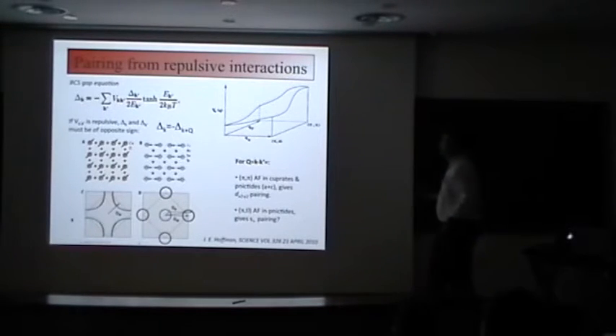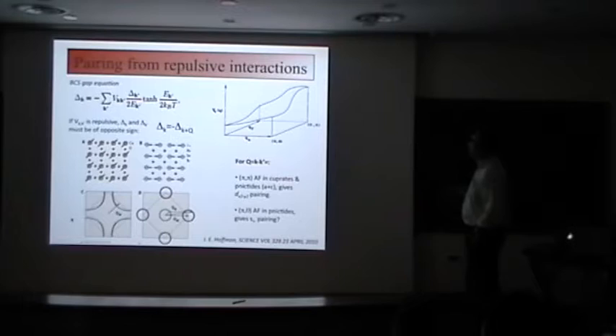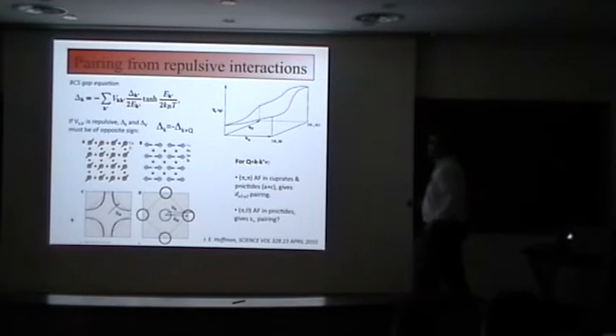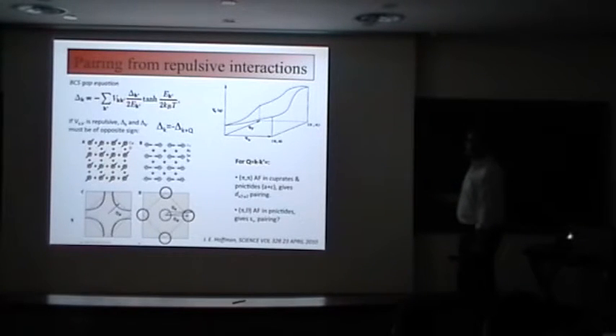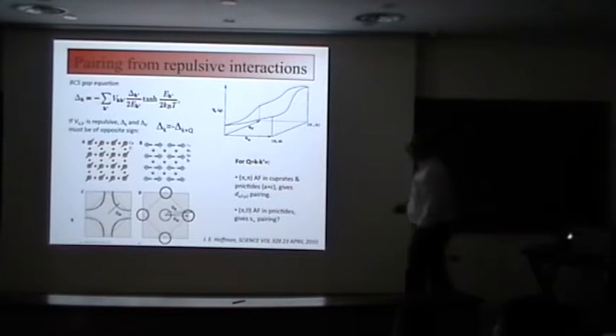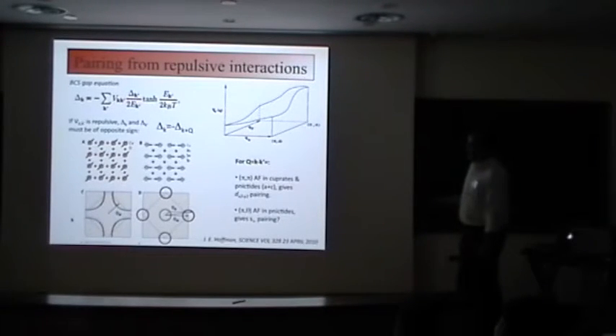If the repulsion is big and peaked at large wave vector, like at pi pi, as in a checkerboard antiferromagnet, then for two states K and K prime connected by that wave vector pi, you just switch the sign. This is from Jenny Hoffman, showing how it relates to the cuprates, where the order parameter pairs electrons at Fermi state K to another K prime connected by the antiferromagnetic reciprocal lattice wave vector, and the gap changes sign plus minus, giving D wave pairing.